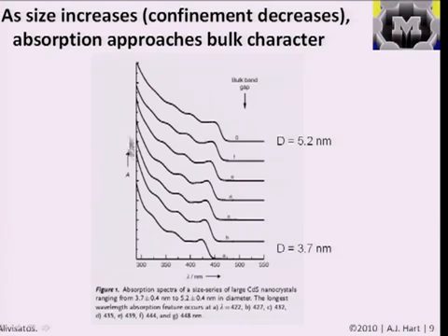So here we have, for example, the absorption spectrum of different solutions of quantum dots. This is the intensity of light absorption, and this is the wavelength. And you can see that the spectrum varies as the size changes. As we go from a relatively smaller size, about 4 nanometers, to a larger size, 5 nanometers, we can see that the energy of this peak is decreasing, and we're approaching an energy that corresponds to the bulk band gap. So if we looked at, for example, bulk cadmium sulfide, which is this material, we would see the spectrum approaching closer to this position.